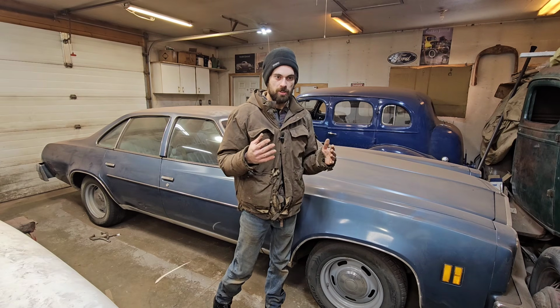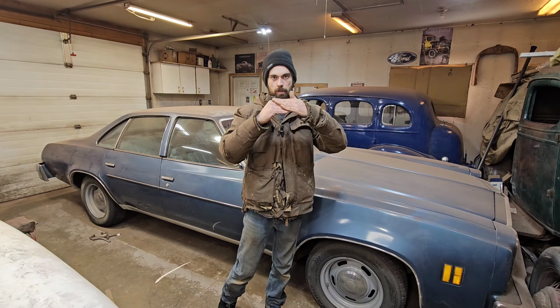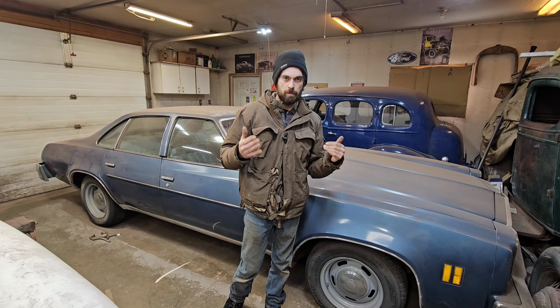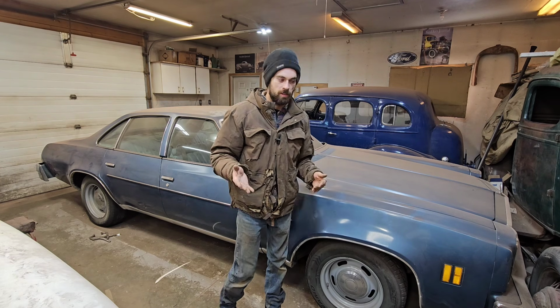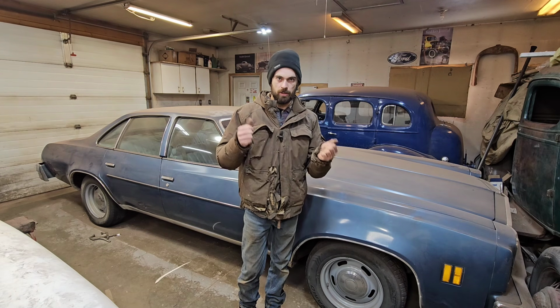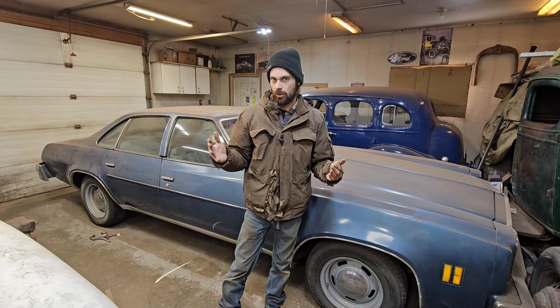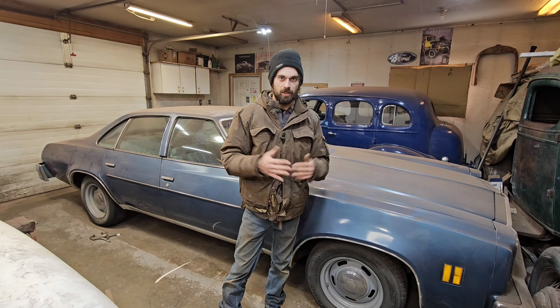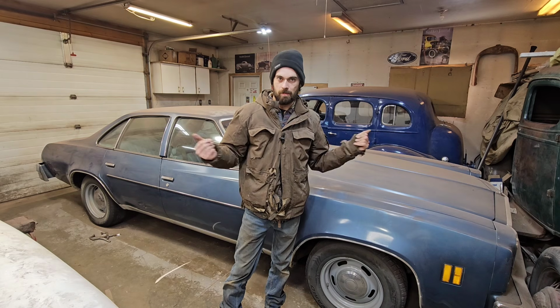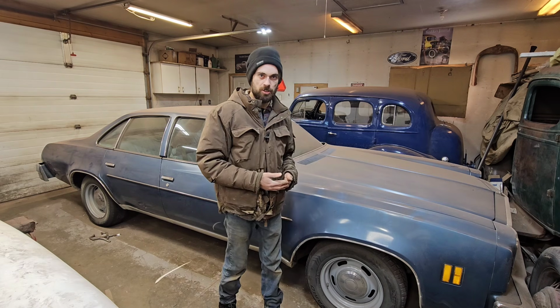The other thing with the butt weld is that anytime you weld a panel, whether it's lap welded or butt welded, there's always going to be that shrinkage from the heat from welding. And yes, you can control it, but what happens when it gets out of control? Well, with a butt weld, we have full access to get in and hammer and dolly and correct that shrinkage. And I have lots of videos showing how to fix that on my channel. If you don't believe me, we can weld something this long, and I've done it in several videos in the past where we weld a big long seam, intentionally destroy it, and then I show you how you can correct that. So it is possible. Again, a learned skill.